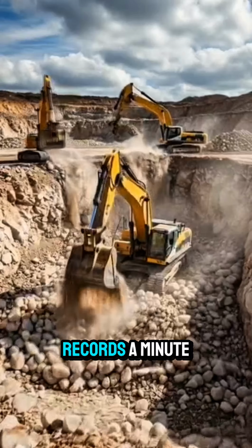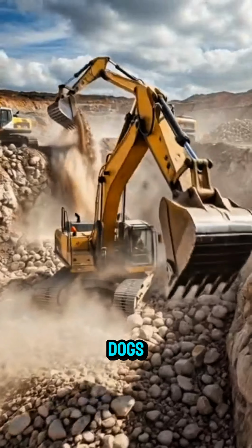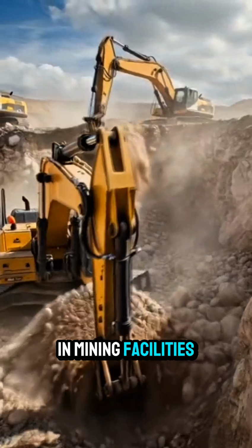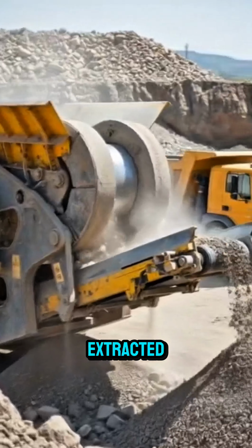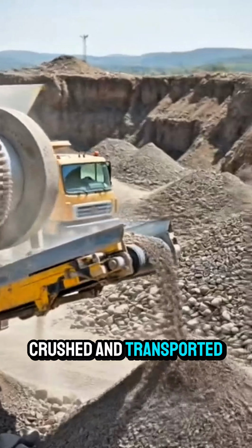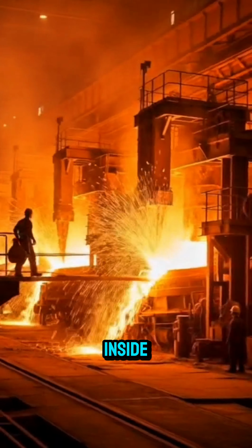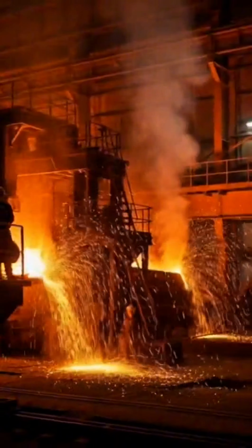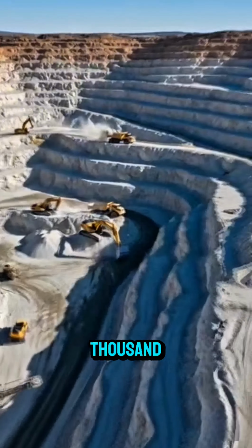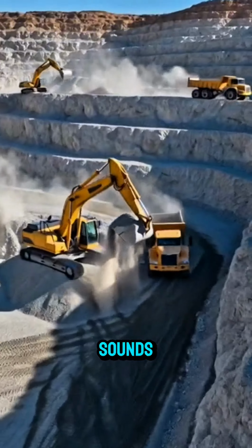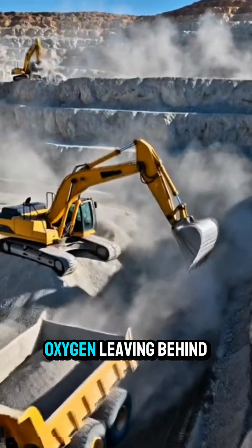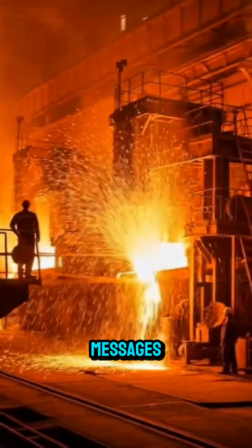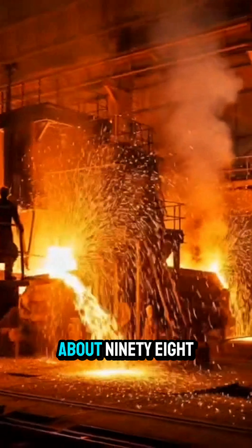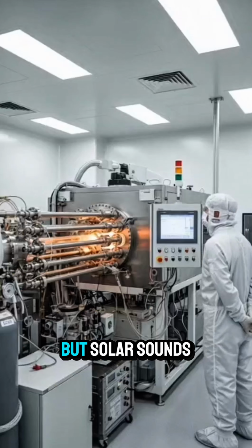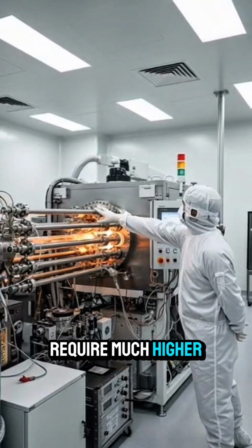It begins with quartz, a mineral made of silicon dioxide. In mining facilities, quartz rock is extracted, crushed, and transported to refining plants. Inside electric arc furnaces, quartz is combined with carbon and heated to approximately 1800 degrees Celsius. This intense heat removes oxygen, leaving behind metallurgical-grade silicon, about 98% pure. But solar cells require much higher purity.